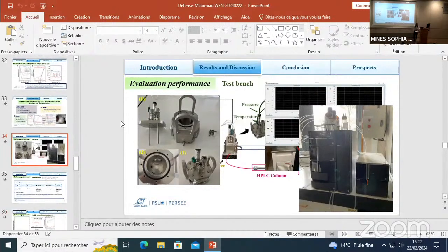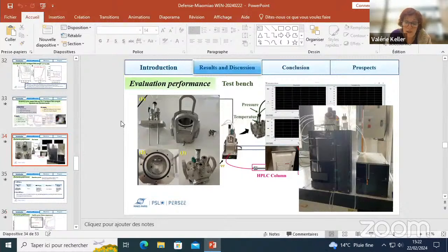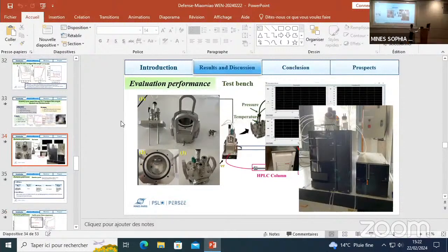Yes, okay. They are using different solar light and different conditions, and it's difficult to compare. So when we compare methanol production, we should be careful about what kind of conditions they were using. Because your higher activity is perhaps the result of different irradiance of the lamp. Perhaps you have 10 times increased irradiance compared to what is given in literature. So you have to be careful about that, okay? Yes.